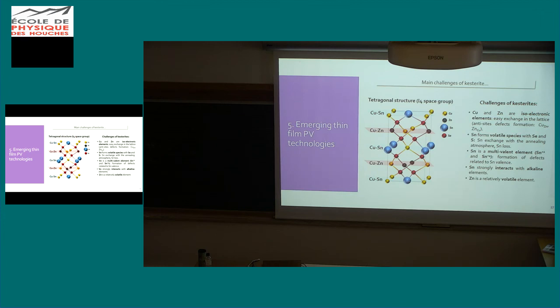Tin has a lot of problems associated with it. First, it tends to form volatile species with selenium and sulfur, so keeping tin in your layer can be extremely challenging. Tin is a multivalent element, and stabilizing the valence of tin in your structure can be a nightmare.